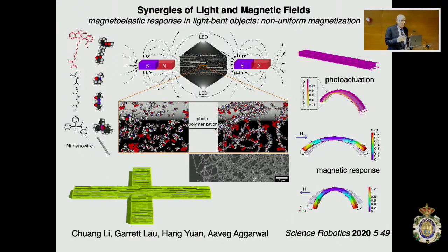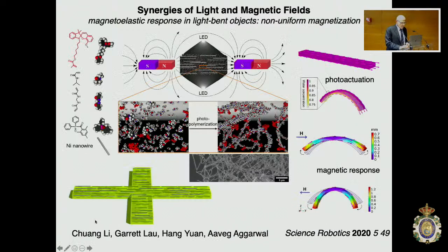So this is now a composite of nickel nanowires and soft material, so that we could get response to a magnetic field, because the nickel nanowires are ferromagnetic. Okay, so I'm going to show you that material. It's yellow. And this material, as you see here at the bottom, that's a schematic. It's just a cross. We cut it.